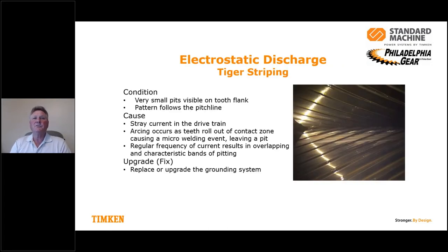Electrostatic discharge, a little harder to tell. I see here we've listed it as tiger striping. There's many different ways to describe it in the bearing industry. They might call it Brinelling or something of that nature. So the condition is very small pits that are really visible on the tooth flank, and they usually follow the pitch line. What's the cause? Well, a stray current in the drivetrain. Something is introducing a current through the gearbox. And the arcing occurs as the tooth rolls out of the contact zone.